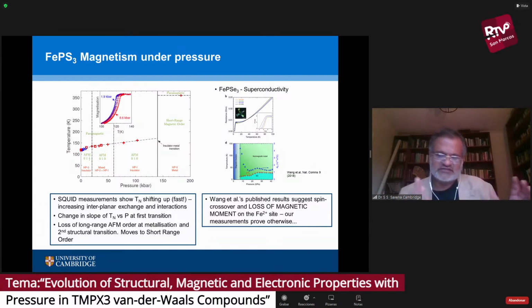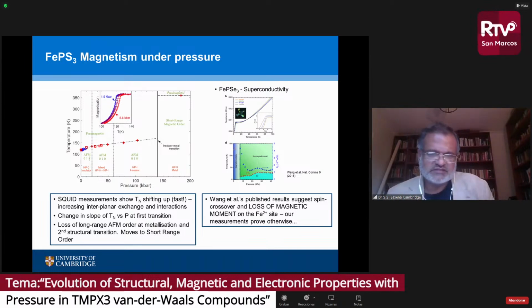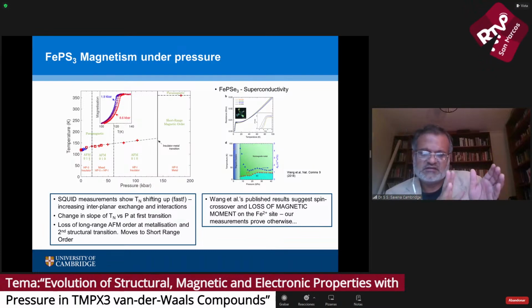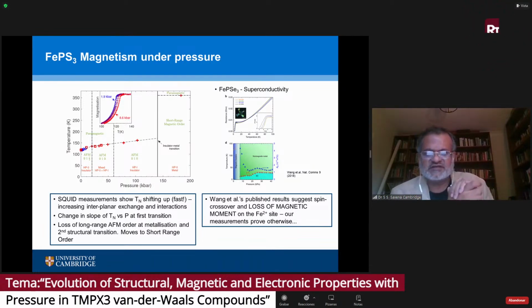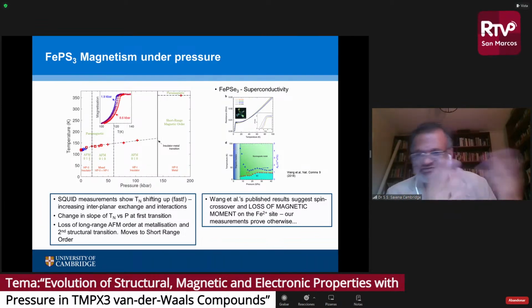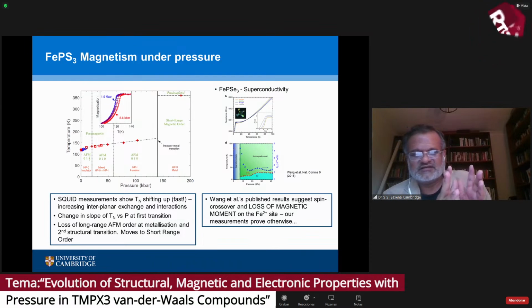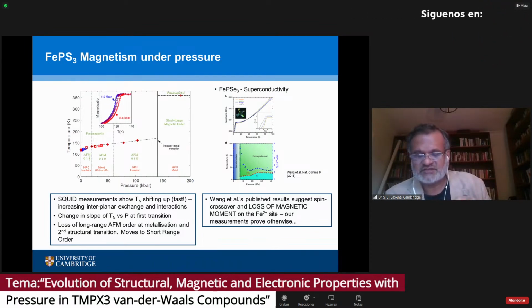So that by itself is very interesting. Now, just returning to the original question very briefly: what about superconductivity? We do have a hint of a non-normal, abnormal, special, or strange normal state, but in this material so far, superconductivity has not been observed, and there can be several reasons for that. One could be that upturn that happens at lower temperature, and perhaps we need to go to higher pressures. Perhaps we need to go to lower temperatures than we have, and all of that is being done.